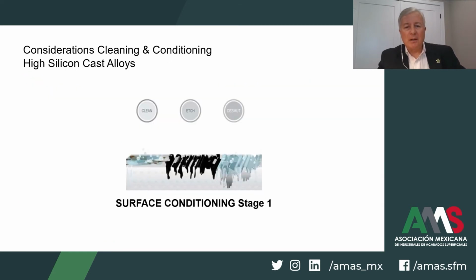Depending on the aluminum alloy and the surface condition of the aluminum casting, the final requirements for a given color or the visual appearance of the casting needs to be determined, which products are required. So in rare cases would we need 5 preparation stages, but with high quality demands for some applications, some types of cast alloys, we have a full toolbox available to process all ranges of high silicon cast aluminum with stage 1 and stage 2.